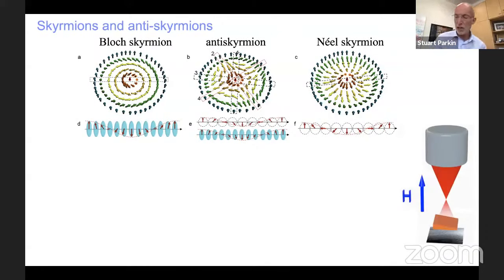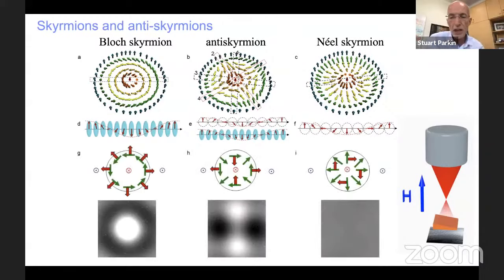So now, how do we detect these objects? And one way, very useful way to detect them is with Lorentz microscopy. Shown in this cartoon, you simply pass a very high energy beam of electrons through a layer thin enough that the electron beam is transparent, and you look at the deflection of the electrons through Lorentz effects. And so if you have an in-plane magnetic moment, as we do in these Bloch and Néel skyrmions and anti-skyrmions, there's an in-plane component of the magnetization in otherwise these perpendicularly magnetized materials in the domain walls. And in the case of the Bloch skyrmion, the Lorentz force causes the electron beam all around the circumference of the object to be deflected either inwards or outwards. And so in the Lorentz micrograph, you will see a circular spot of increased or decreased electron intensity shown on the left. This is a simulation.